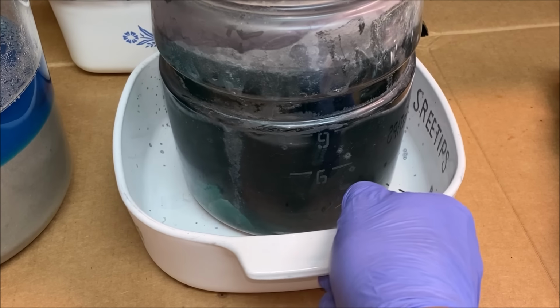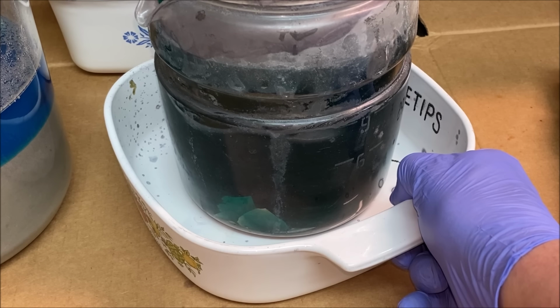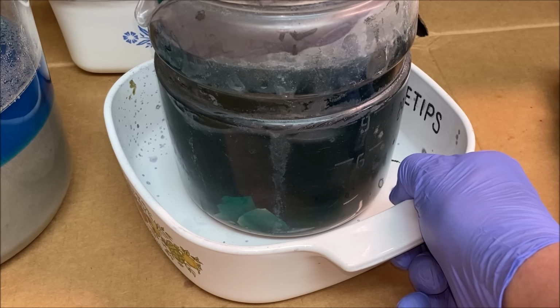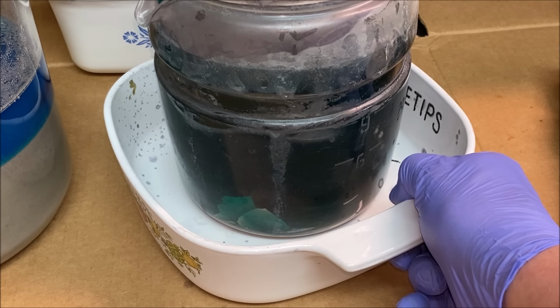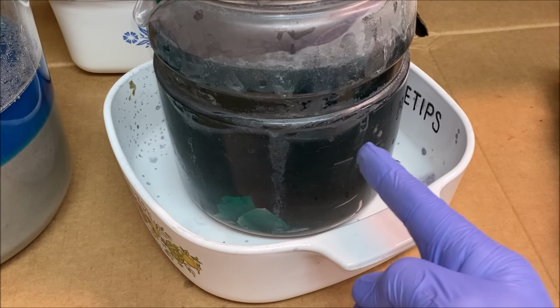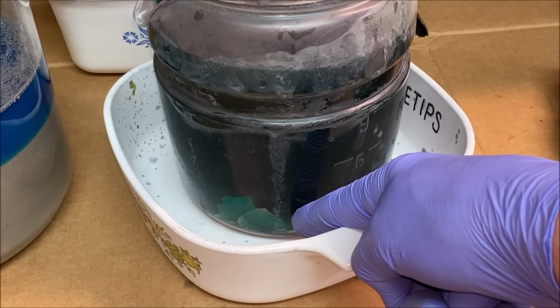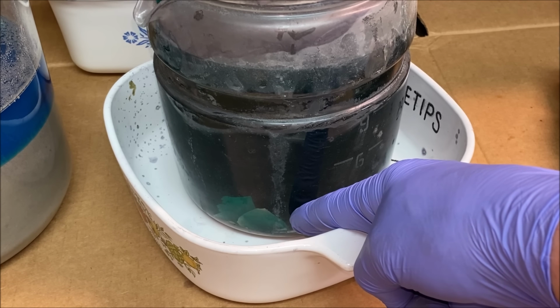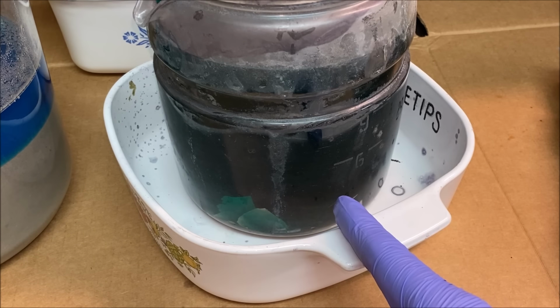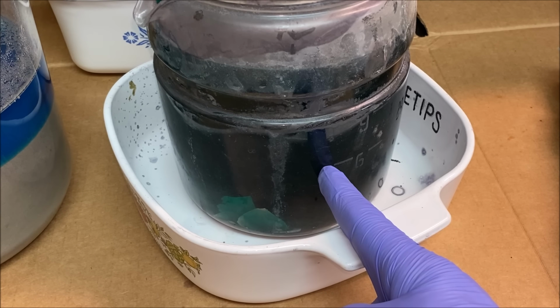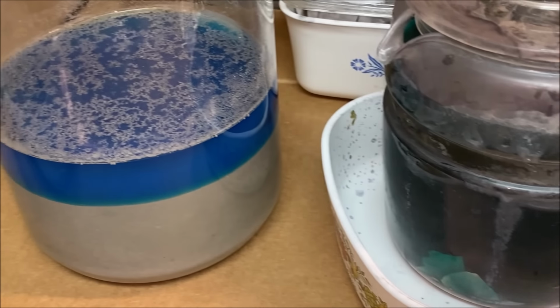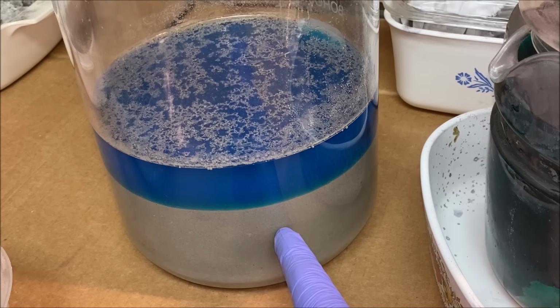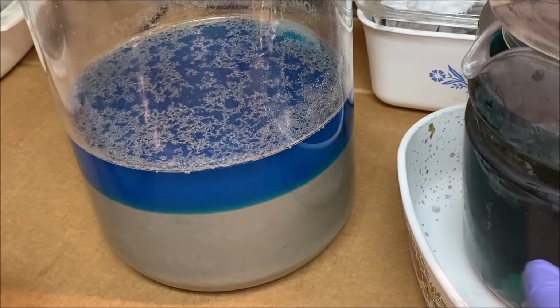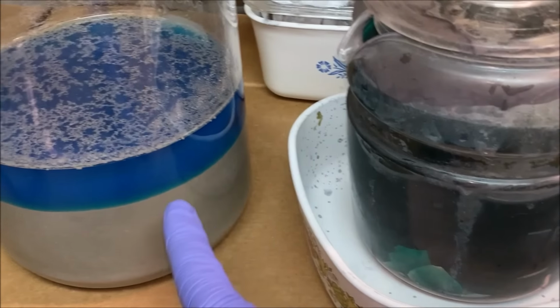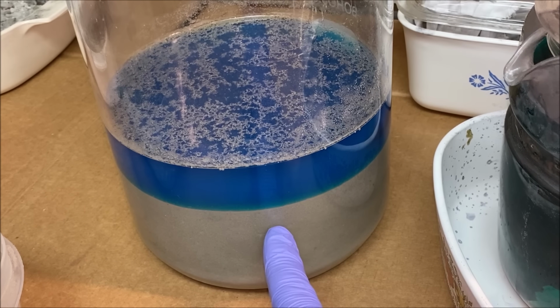So we have some silver nitrate solution here that we poured off and recovered from the inquarted gold. We inquart the gold with silver, sterling silver, and then we pull it back out with nitric boils. I add it to this jar, and then I add some additional pieces of silver so that all of the excess nitric gets consumed. And then I take this solution and filter it, and then I add pieces of copper to it and cement the 98 to 99% pure silver powder out of this solution onto pieces of copper in this jar.